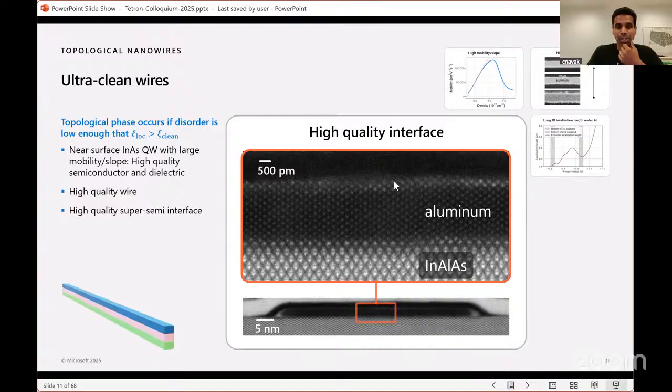What you see up here at the top is the oxide. So we oxidize the aluminum, which stabilizes it, because otherwise aluminum would tend to de-wet and ball up and you get droplets. So we stabilize the wire by oxidation, and you can see some oxide forms up here, a few nanometers on the top. Is that aluminum oxide? This is aluminum oxide on top, correct.